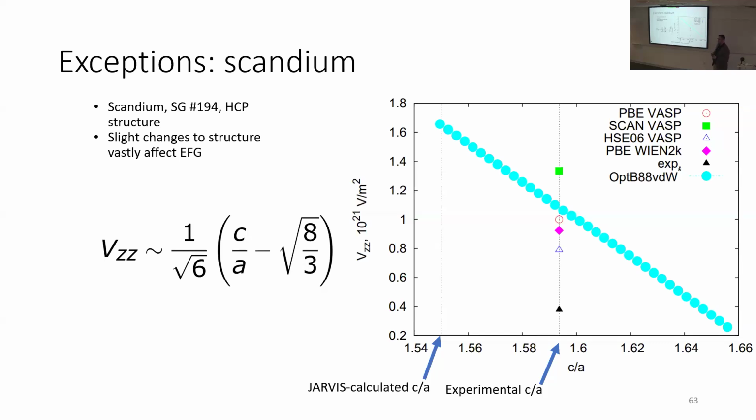The goal, again, was experimental prediction. And so we chose materials which had previously measured electric field gradients from very highly reliable experimental predictions. We were able to take those NQR frequencies and convert them to EFGs and comfortably compare them. So I wanted to see how well my calculations were doing in comparison to that. And for that reason, we didn't use relaxed structures. We could have used a relaxed structure, but we wanted to see, if we used the exact crystal parameters at that temperature that the NMR experiment was performed, how well would they compare to each other? And so we picked those materials which had reliable crystal structure data and reliable EFG data from experiments, so that we can compare them holistically and fairly to each other.